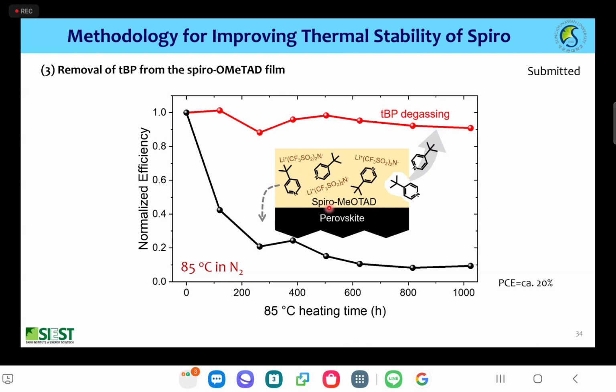Then after making this spiro compound, we degas the TBP, and then we found that there is almost no TBP left in this spiro compound, and it is quite stable at the high temperature, 85 degrees C. But the efficiency is a little bit lower after TBP degassing. So this is an issue to be addressed.